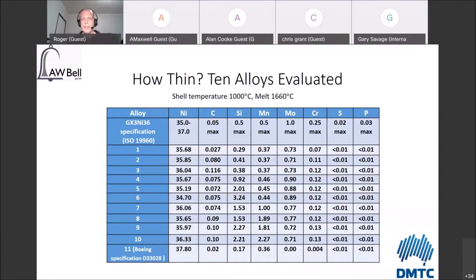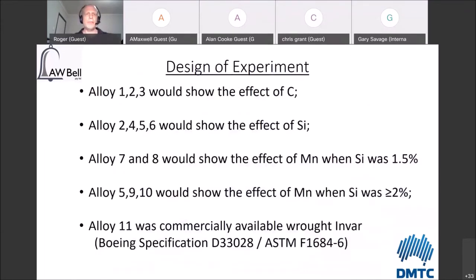So, these are the 10 alloys that we manufactured, starting at shell temperature 1000, melt 1660. Basically, we're going down to very, very thin wall thicknesses, so everything's really at the hot end of what you do for investment casting.